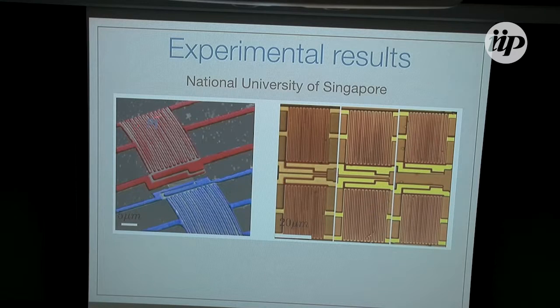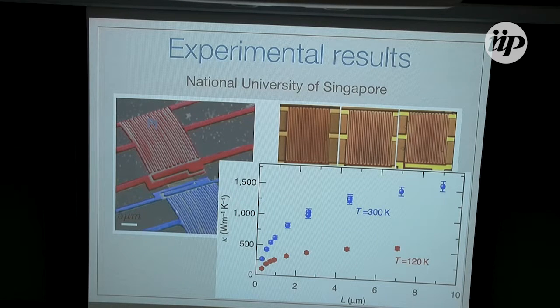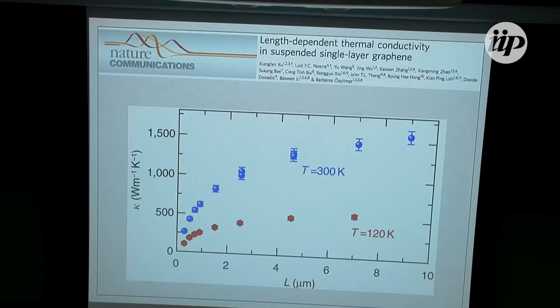The experiments are quite amazing. So here you have this platinum electrode as well. You pass a current here, this guy heats up, and the graphene patch is here between these two guys, okay? So it heats up here, here's at a lower temperature, graphene transports the heat here. And they could not only fabricate one of these structures, but they could fabricate structures varying the space between the circuits. Therefore, you could change the length of the graphene patch between them. And then when they did that, this is a linear scale, right? They saw a nice increase of the thermal conductivity with the length, both at lower temperature and at 300 K.